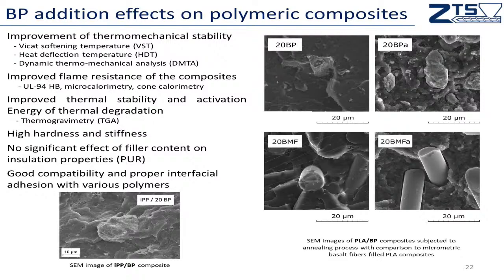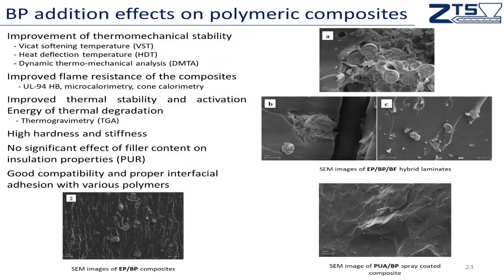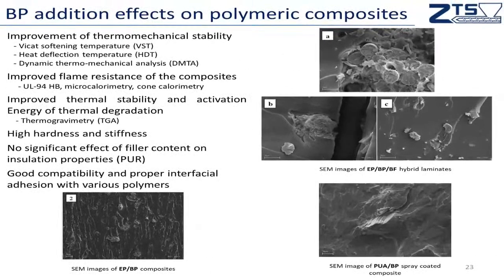And when we change the slide to the next one, of course, we can see that in the case of the reactive systems and thermoset materials, the samples, due to the partial reactivity with the monomer in the case of the isocyanate-based materials, so the polyurea and the polyurethane, are well saturated. Here we can see the epoxy composites where the cross-link density around the particles is much higher. So we can see the amine hardener reacting with the hydrogen bonds and giving us the opportunity to achieve really good